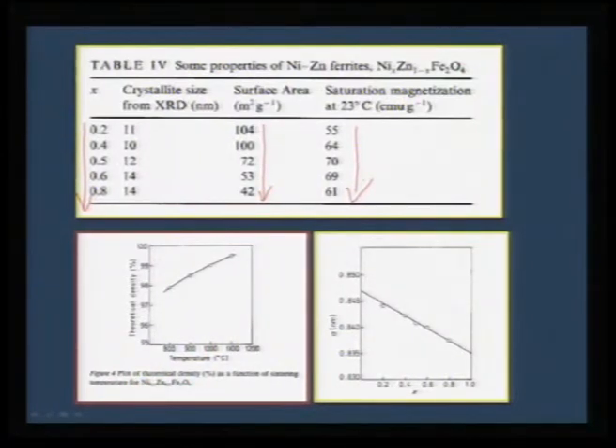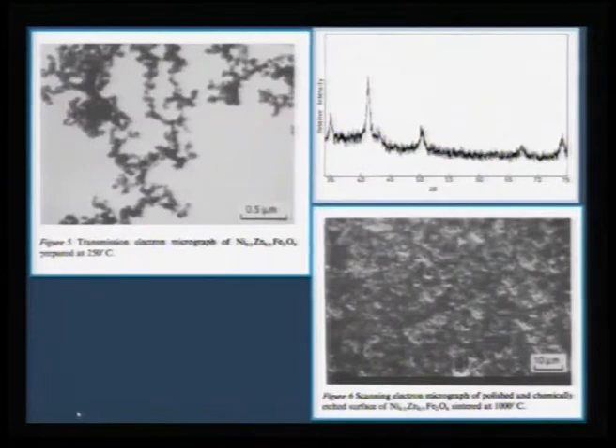And these powders can be densified, and the densification profile clearly shows that you can get nearly 100% sinterability in these compounds because of their fine reactivity. This is the TEM micrograph that shows very clearly these are all of the order of 50 nanometers, and they show a very good scanning electron micrograph, and the nickel zinc ferrite shows that this is a nanophase powder because of the X-ray broadening.